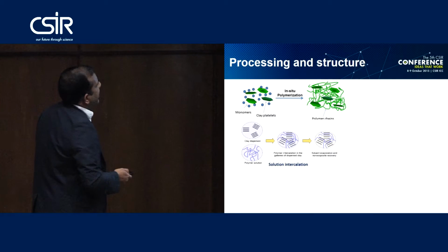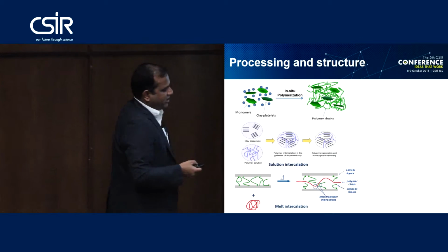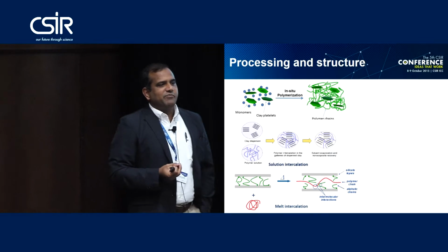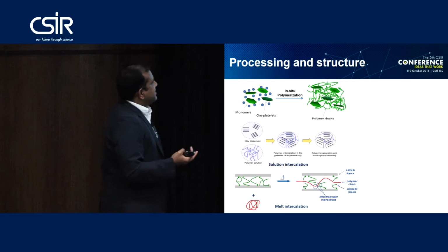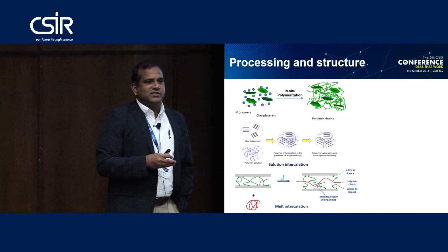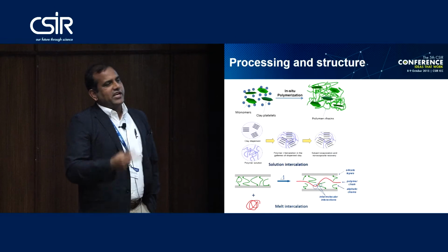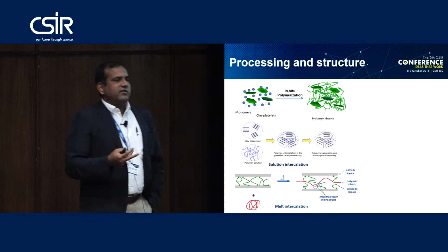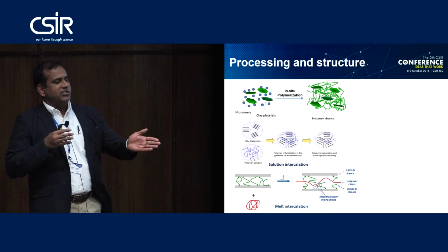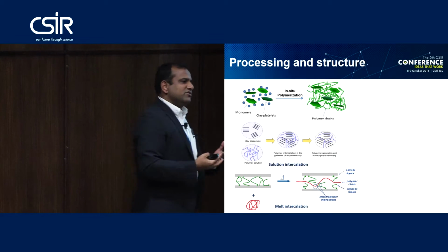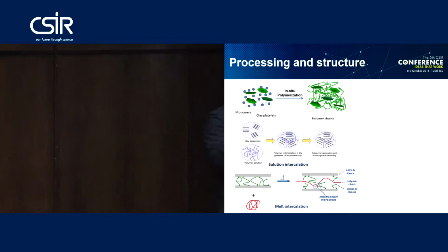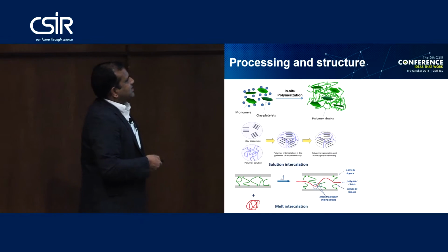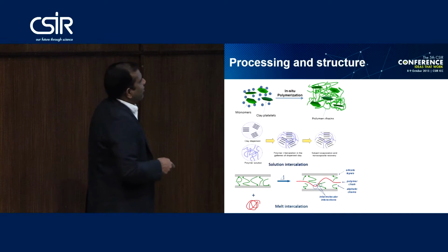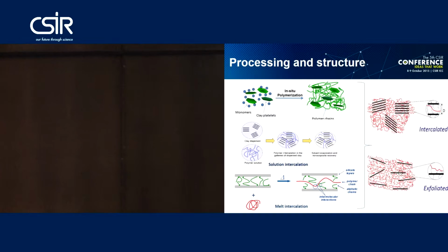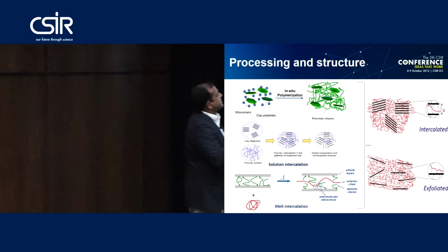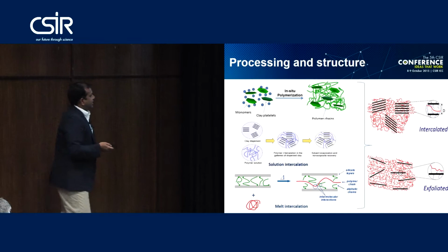You can also get composite materials that way. Another is melt intercalation, where you melt your polymer at high temperature above its melting point, and at the same time add your clay into the melt. You can use an extruder that generates force, and that force helps the macromolecular chains, because in the melt state they have very low viscosity, so they move in. This is the most industrially viable technique, and at the center we are only using melt intercalation. But the ultimate aim is to have a nano level dispersion of your clay platelets in the matrix.